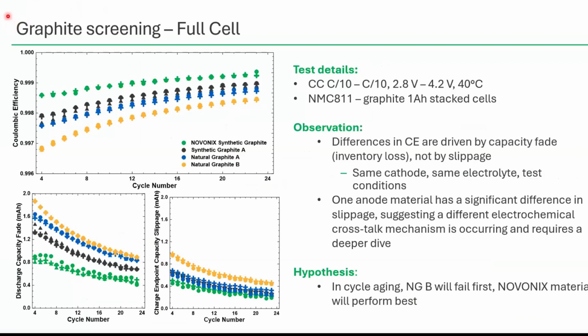Another case study here, very similar again to cathode, is doing graphite screening with full cells. Cells made on our pilot line, all the same cathode, all the same electrolyte, and we're just varying different types of anode. Here what's really interesting is we almost see the flip side of what we saw with cathode, and this is due to where these mechanisms typically occur, where we see these big differences in coulombic efficiency. Again, these axes are really blown up compared to other types of equipment.